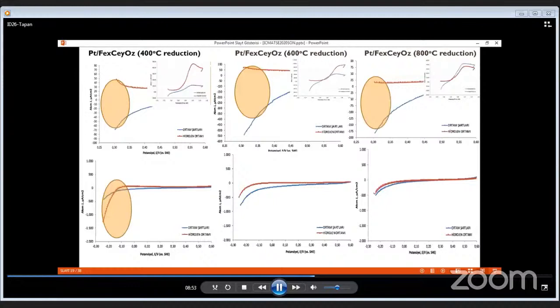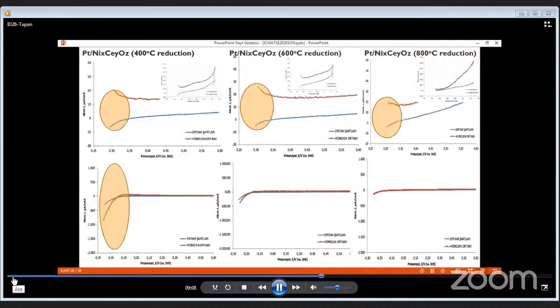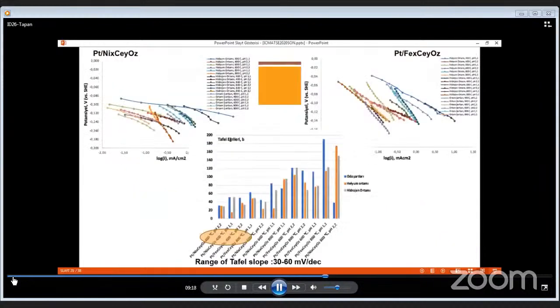Homemade catalysts also show somewhat similar behavior like platinum disk, but interestingly, catalysts reduced at 400 degrees exhibit higher reduction current compared to other reduced catalysts. This interesting behavior, we believe, is due to the induced active volume of this catalyst. Here the same behavior we are also seeing for the nickel series supported catalyst. When we perform Tafel analysis, we have also observed the lower Tafel slope in the range of 30 to 60 mV per decade for catalysts reduced at 400 degrees.